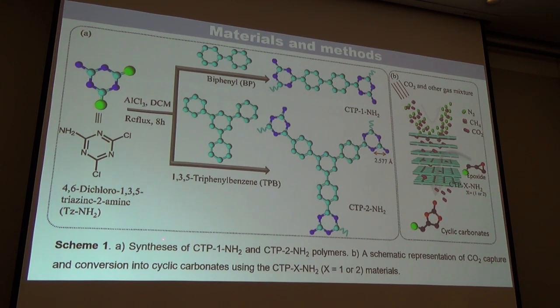So taking these points in mind, we have prepared these two catalysts using the monomer called 4,6-dichloro-1,3,5-triazine-2-amine. We have treated this material under Friedel-Crafts conditions in the presence of two aromatic linkers called biphenyl and 1,3,5-triphenylbenzene, and they yielded CTP1-NH2 and CTP2-NH2 materials. This schematic diagram shows the possibility of using the material for CO2 adsorption as well as for the conversion reaction.